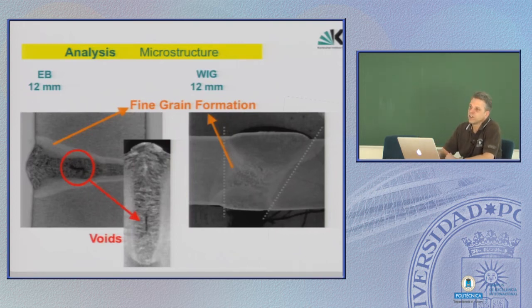And again, you also use additional Eurofer material in the form of typically 2 mm thick wire, and this can produce problems, since this weld is permanently melted at very high temperatures. The one or other alloying element could evaporate, which would change the chemical composition of the resulting weld.